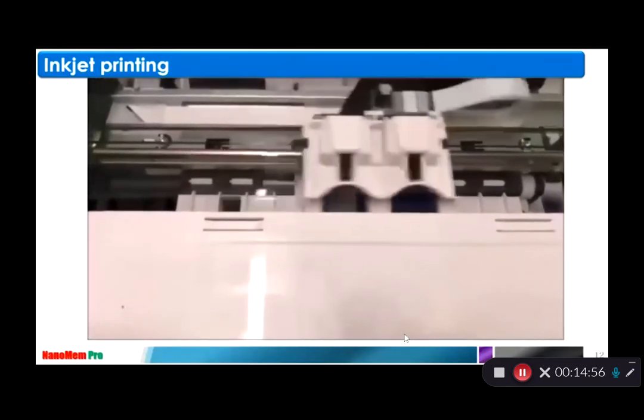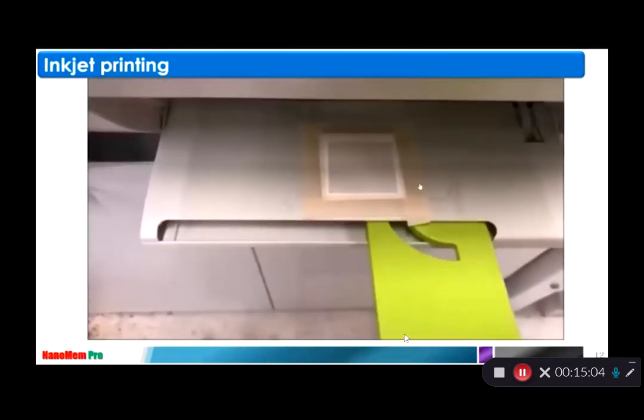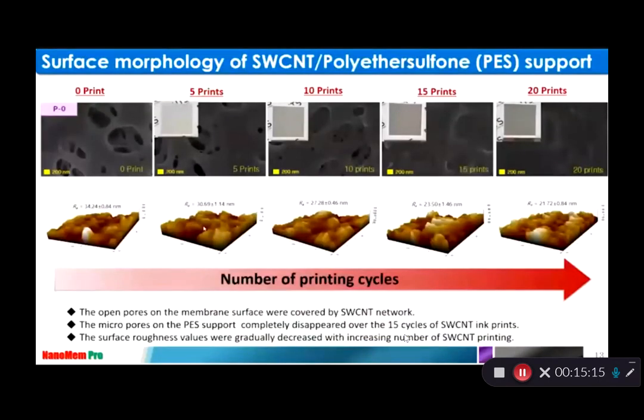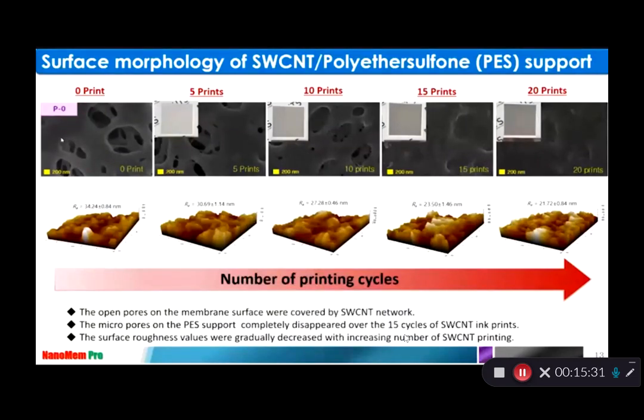All right, so you can see the membrane. We just utilize the SWCNT and then print one time, 10 times, 20 times, and then we look at the different ways of their layer and how this will change the overall membrane characteristics. So we just compare this result. This is the 0 and 5 prints, 10 and 20 times. When you increase the overall printing cycles, you can see how this PES membrane changed.